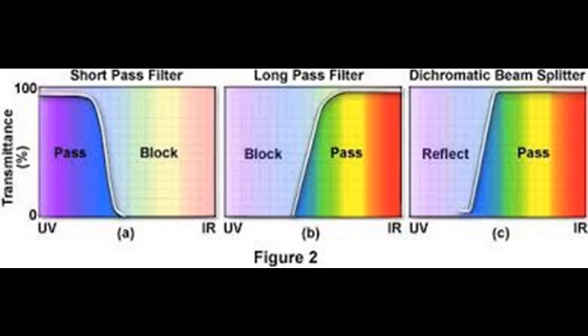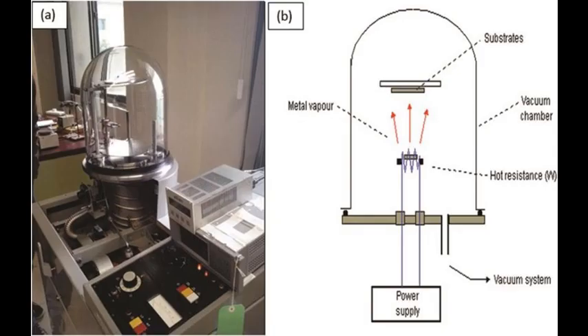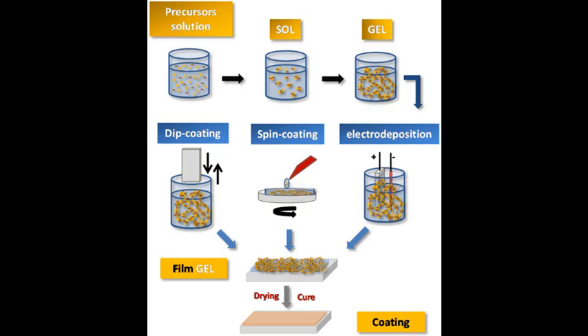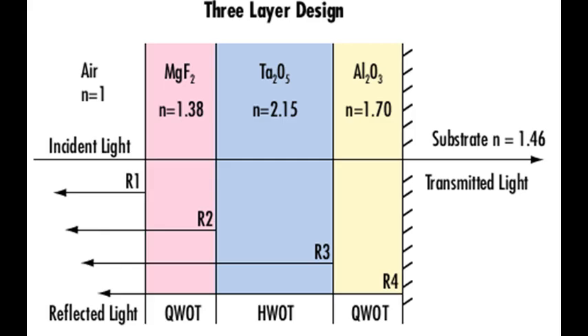How do you manufacture a 1D photonic crystal — layer after layer — to create anti-reflection coatings, blue light filters, notch filters, or bandpass filters? They are made by sputtering, coating through evaporation, or by sol-gel technique. Thin film coatings are created by depositing dielectric and metallic materials such as tantalum pentoxide and aluminium oxide. To maximize or minimize interference, layers are made to lambda/4 (quarter-wave) or lambda/2 (half-wave) optical thickness. These thin film layers alternate between high and low refractive index, inducing the required interference effect.